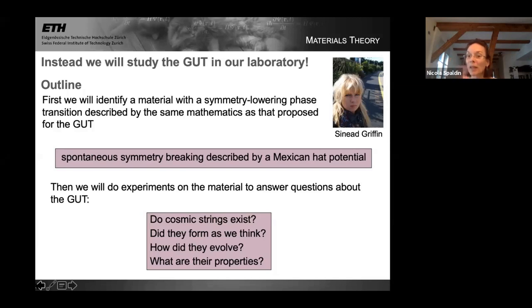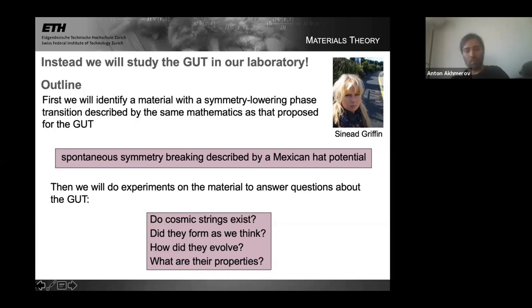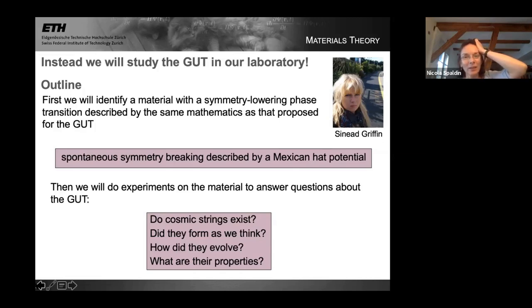In superfluid helium, vortex formation. Liquid crystals, the nematic phase transition in liquid crystals also has the same symmetry. When we look in detail at this equation, what we'll see is that in order to have a measurably different density of topological defects over the experimentally accessible range of passing through the transition, it's really difficult. You have to be kind of lucky with your parameters that you can access, to get across a range. And the other thing is you have to make sure you have no other physics that will dominate. So for example, liquid crystal is really an ideal system, but it's hard to get at the really fundamental underlying U(1) symmetry because liquid crystals also have, just like regular materials, chemistry defects, which then tend to dominate often the behavior of the phase transition.